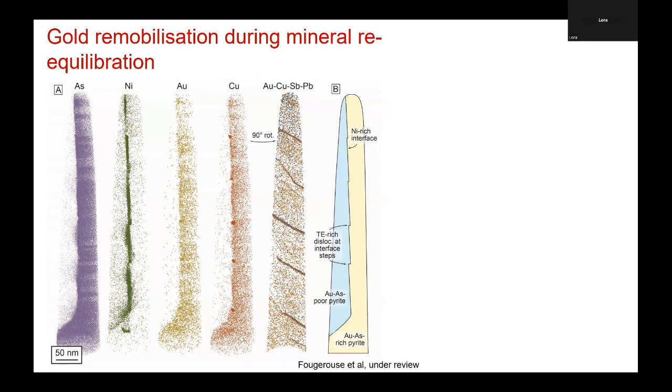And if you rotate that atom probe needle, what you see is that they're basically aligned again in these dislocations. So in this example, again, we have trace element enriched dislocations, and they are located right at that contact between the two domains. Now, maybe you're going to have to believe me here, but when I squint really hard, what I see is steps. Every time I get one of these dislocations, I've got a step in orientation of my boundary. Can you see it? I'm glad some people are nodding.